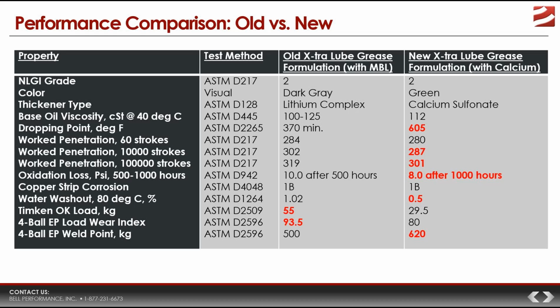They take a sample of the grease, they put it into a special machine, and they work it. They turn it over, or they work it for 60 strokes, and then they measure the thickness. Then they work it for 10,000 strokes, a much longer period of time, and they measure the thickness. And depending on if it's specified, they will then work it for 100,000 strokes, and they will test the thickness, and see how the thickness of the grease changes within the 3 points.